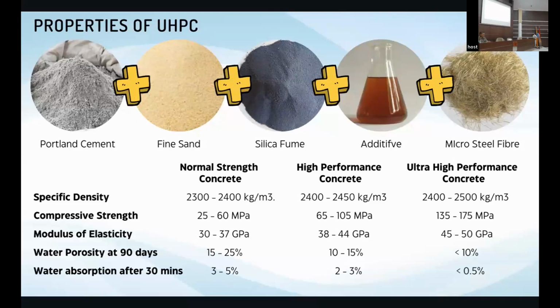Right. So normally we have normal strength concrete from 25 to 60 megapascal. Right. And then you have high performance concrete. The range can go from 65 to 105. This one is used by KLCC and Burj Khalifa engineers. Now, the latest one is no longer high performance, but ultra high performance. The density remains the same. So imagine, the density remains the same. Strength is increased up to twofold, up to 2 times.